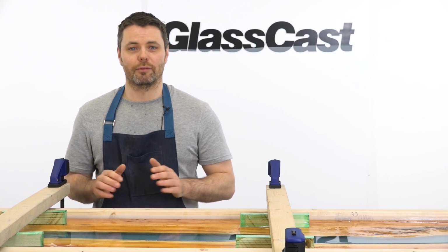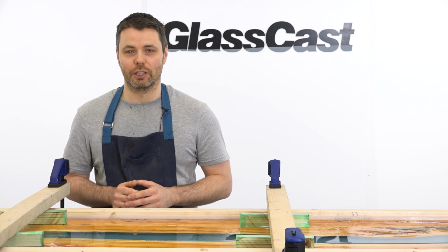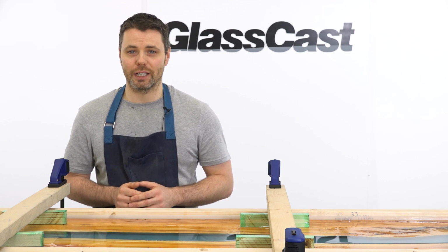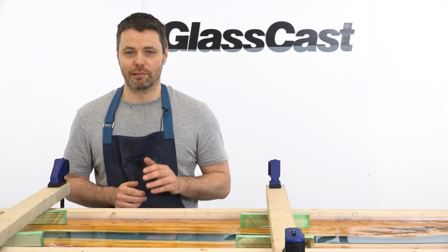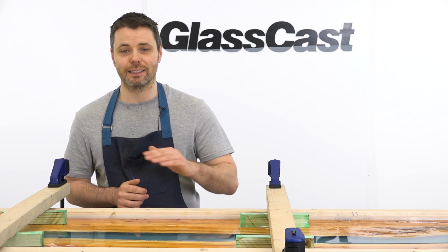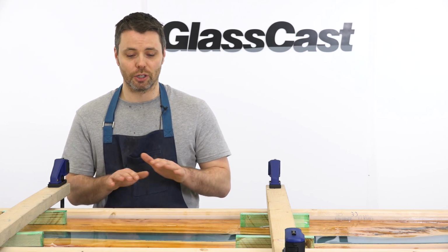With the final pour now finished, we just need to leave the resin to fully cure. This will take at least 48 hours at 20 degrees, and it's really important in that time to maintain the temperature throughout and keep dirt and dust away from the surface.